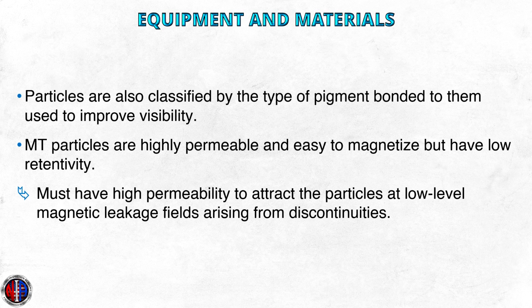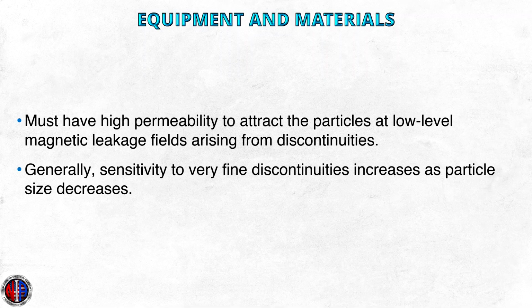Dry powders often use iron filings, while wet particles generally use iron oxides. MT particles are highly permeable and easy to magnetize but have low retentivity. Low retentivity is crucial in order to prevent the particles from retaining magnetism. If the particles were to retain magnetism, they would eventually clump together and become useless. The particles can be irregularly shaped, spherical, flakes, or rod-shaped.